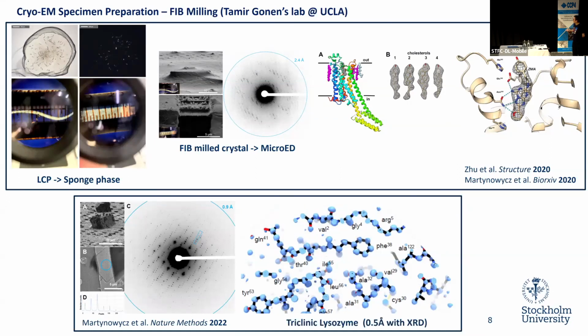But the problem is that what they collected was 0.9 angstrom. They could do direct methods, direct phasing with this data, but this is triclinic lysozyme. For X-ray, the resolution is 0.5. So the take-home message is if you can do X-ray, if you have large enough crystals, still collect them at a synchrotron or home source, you're still going to get better data by having X-ray.